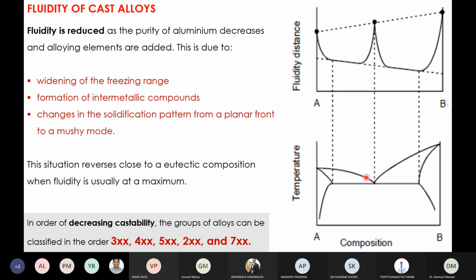So the freezing range can also dictate your mold filling ability, or the fluidity, because when you have a wide freezing range alloy, you are passing through the liquid plus solid zone, and that solid phase can hinder the movement of your fluid, overall on a macroscopic scale through the mold, or it can also affect the movement of your fluid when your dendrites are forming. Okay, so there are other aspects which can affect the fluidity of your casting. Similarly, if you have an alloying element which forms a large number of intermetallics, and the morphology is not suitable, that can also interfere with the flow of your liquid.